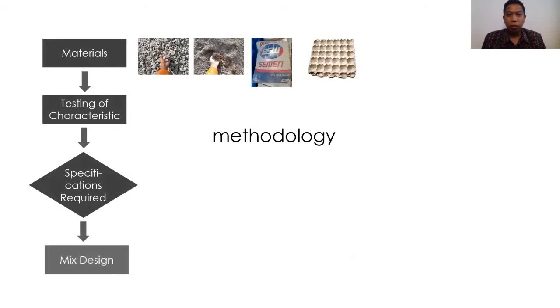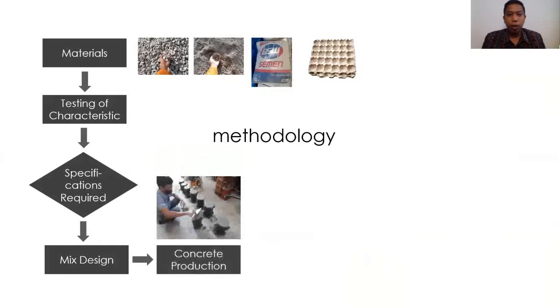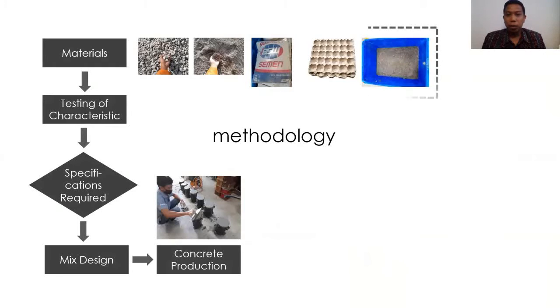Mix design was carried out to obtain a compressive strength of normal concrete with target f'c 30 megapascal. The specimens were made in 4 sample variations for the percentage of egg tray waste, with variation of 0% for normal concrete, 1%, 3%, and 5% for variation of substitution of fine aggregate with egg tray waste. The egg tray waste used is cleaned of dirt, and is made into pulp to be mixed into the concrete.